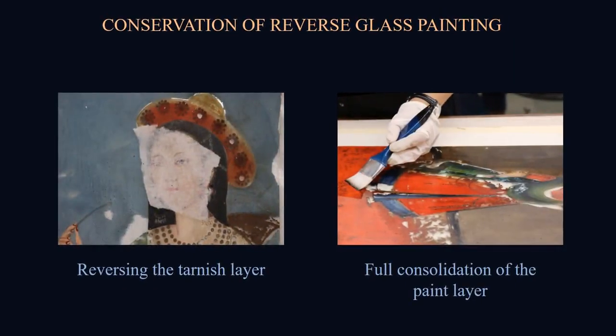It is important to reverse the tarnishing layer to maintain the aesthetic value of the object. The layer of tarnishing was reversed by treating the paint layer with a mild oxidizing agent. This oxidizing agent converts the black lead sulfide to lead sulfate, thereby allowing the original colors to be displayed. Then the full consolidation of the paint layer was undertaken by using a synthetic adhesive.